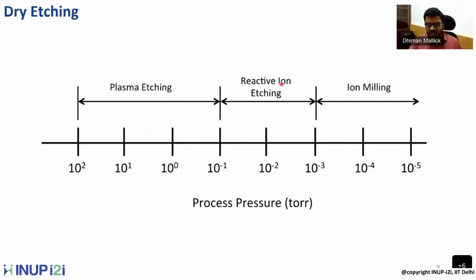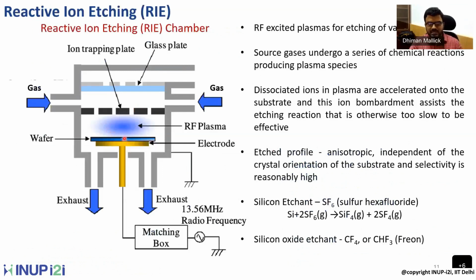Because reactive ion etching is a combination of both, here you follow an intermediate path. The process pressure is also affecting the mean free path. So the mean free path is not as large as in the ion milling process, and the momentum transfer is not as much as in ion milling. But on the other hand, it has the plus point of plasma etching, that is the chemical reaction. So the momentum transfer is also happening, as well as the transferred ions participating in some kind of chemical reaction. Based on that, the etching process is happening.